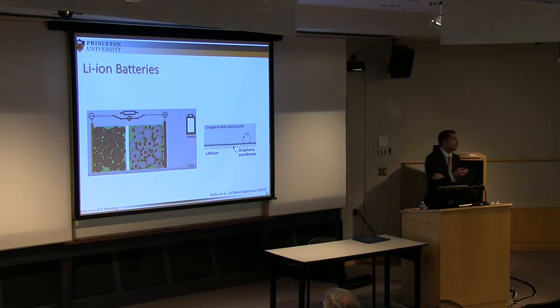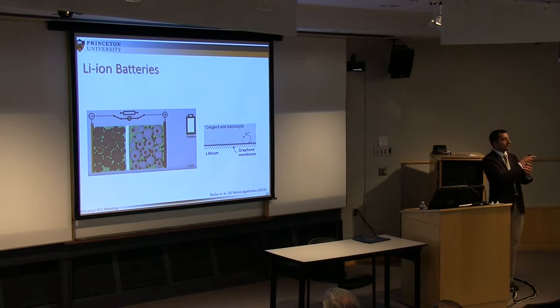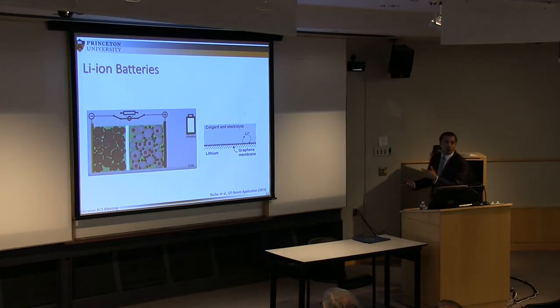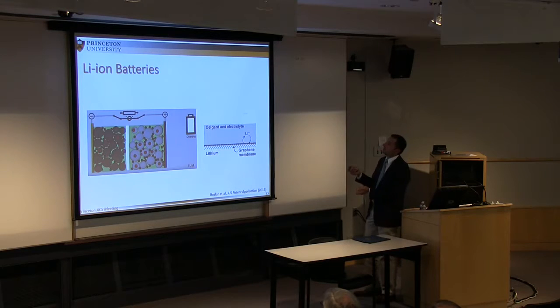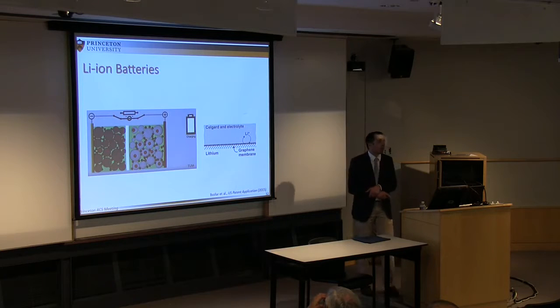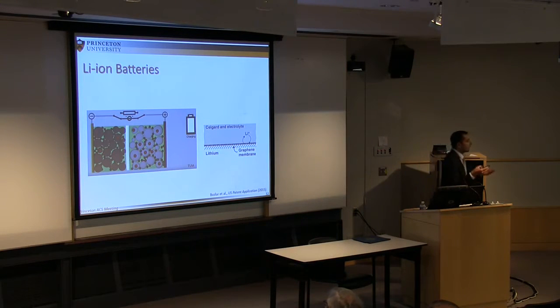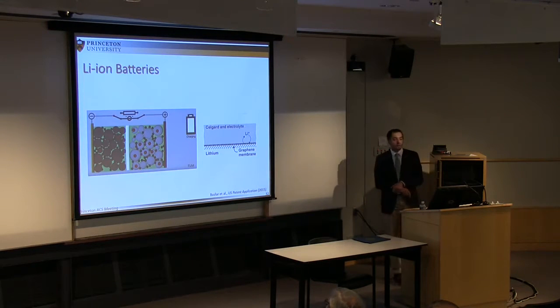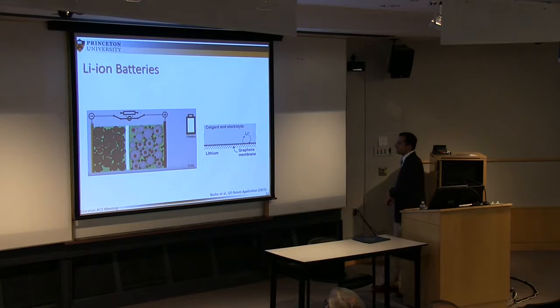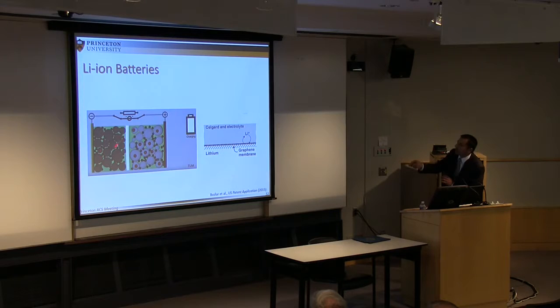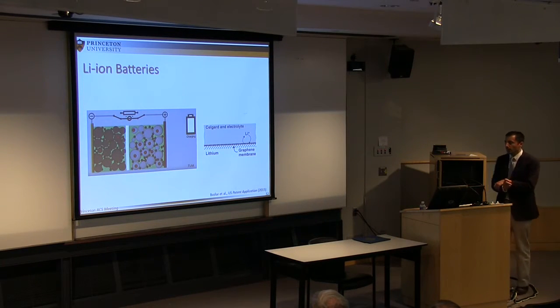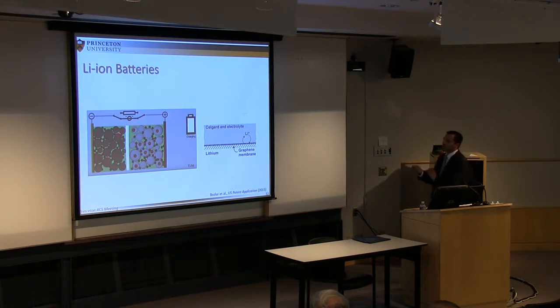So the working principle is you shuttle lithium ions back and forth depending on whether you are charging or discharging your battery. If you are charging your battery, these red lithium ions migrate to the other electrode, the anode, and intercalate between the graphene planes of graphite. So that's a good chemistry. In between, another important component is the separator, which prevents shorting, and in the presence of the lithium source, the electrolyte.